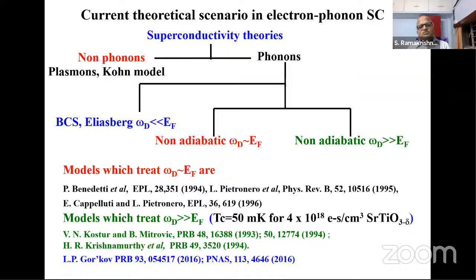So what is the superconductivity here? As I said, there are two approaches to the high TC problem. One is you try to look for the same mechanism, electron-phonon interaction, and apply pressure, the way people have achieved 288 Kelvin this year at 2.7 million bar. Then try to work with these compounds, do an alchemy and try to see whether you can get the superconductivity at reduced pressure. Or you go away from the BCS and look for a new mechanism for superconductivity.